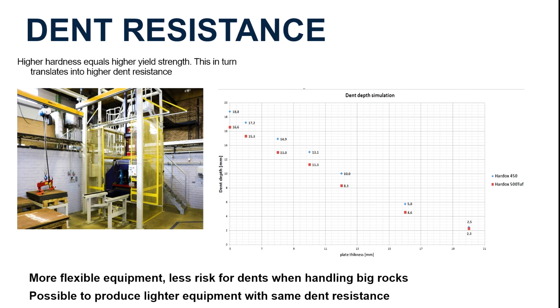A little bit about dent resistance, because this can be important when it comes to building tipper bodies. If you load tipper bodies with a big rock or something, you have a risk of causing a dent in the bottom of the tipper body. But dent resistance of a steel is related to the strength of the material. In this case, Hardox 500 Tough will have much higher dent resistance compared to Hardox 450. So you can reduce the thickness of the tipper bodies to save weight, but keep the same dent resistance, using thinner material.